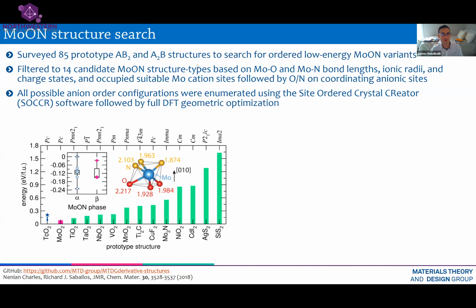So what Nathan did was he asked the question: if I take this composition, molybdenum oxynitride, is it going to be stable in the rutile-like structure? He searched exhaustively all possible AB2 or A2B structure types and found that the lowest energy structures using density functional theory were these two prototypes, this technetium dioxide and this molybdenum dioxide structure. These are very similar to the monoclinic structure of VO2, which I showed you earlier. In fact, the structure of molybdenum dioxide is indeed that one.